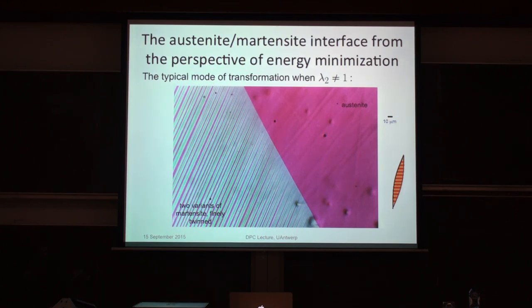Okay? And then you take that calculation and compare it with the experiment. It's a very rigid calculation. You give me this so-called twin system, the two variants, and the way they're arranged, and then I get just four possible normals to this interface, and two possible volume fractions. Now, there's one more piece of information, and that is that this explanation could not be exactly correct, because it would suggest that to reduce the energy in this layer, I just keep making these twins finer and finer and finer, and of course, they have a certain scale. That's understood as well, and the explanation is the following.